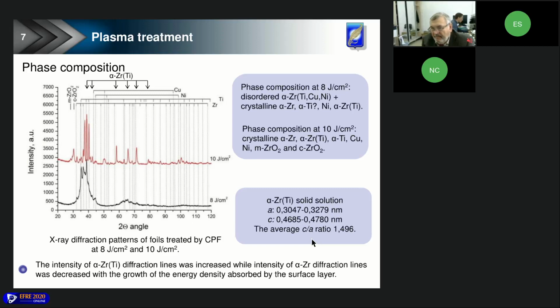And one more remark concerning the slide. It should be noted that formation of zirconium nickel or maybe zirconium copper intermetallic phases in the surface layer was also possible after plasma treatment at 10 joule per square centimeter. But the angle position of some intermetallic phases' diffraction lines, for example, well-known Cu51Zr14, coincides with the angle position of other phases revealed in the analyzed layer. So, I mean, no separate diffraction lines of intermetallic phases with high intensity were found in this diffraction pattern.